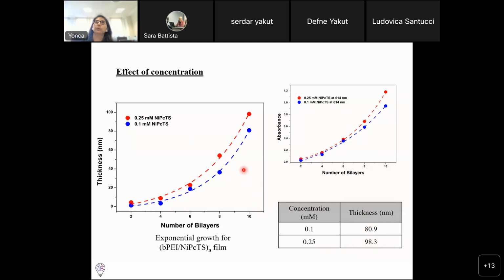This might be due to a couple of things. First, it can be that maybe the phthalocyanine is interpenetrating into the underneath layer, or vice versa, the branched polyethylenimine, so that they are not providing distinct layers on top of each other. So either one of them is swelling and diffusing. Or in addition to electrostatic interactions, they may have other kinds of molecular interactions as well, like hydrogen bonding and so on. So it is not the only way.